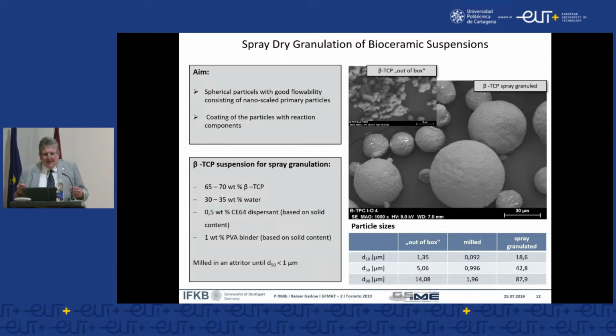So this is essential, and for example a beta tricalcium phosphate, beta TCP suspension was used, with a very high solid content, up to 70%. The liquid in this case was water. There are some special polymer surfactant additives and a small amount of binder like polyvinyl alcohol, for example. And as I mentioned before, the original powder is passed through a fine milling in an attrition mill, and in any case the primary grain size is smaller than 1 micron. That means out of the box of the supplier, this is a very fine material. Then we have the milling operation and the high value adding by the spray drying granulation.